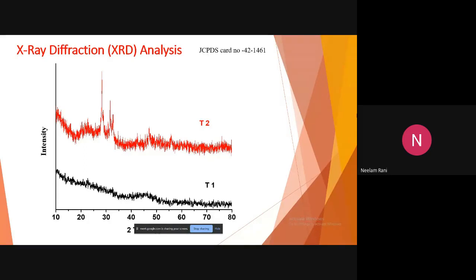When the preparation of the material is starting, lots of starting precursors and impurities are present in the prepared sample. So after annealing, we can see a sharp peak near the range of 28.29 degree, and these definitely match with the JCPDS card number 42-1461.